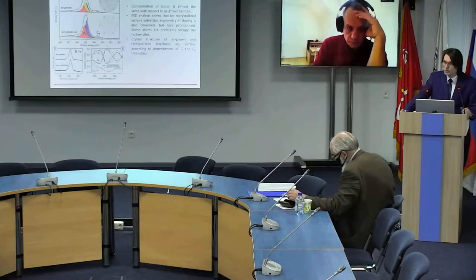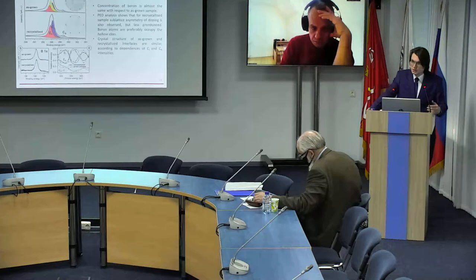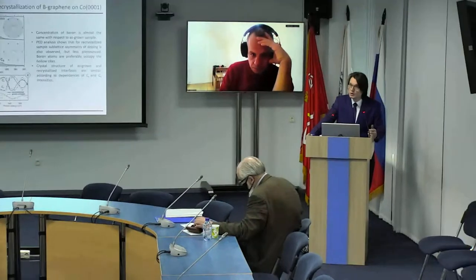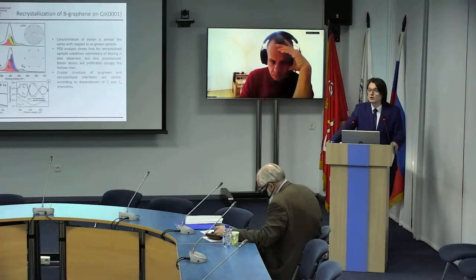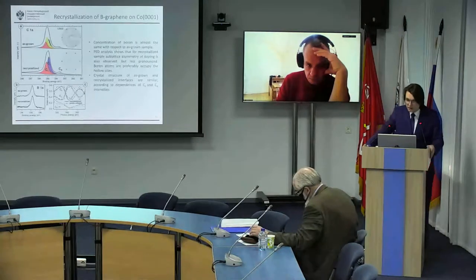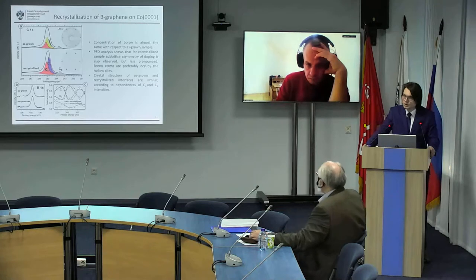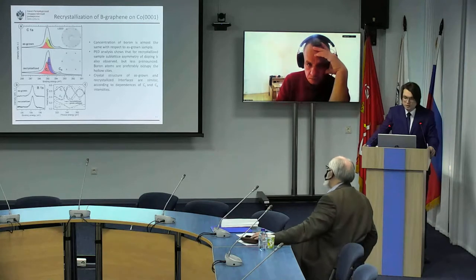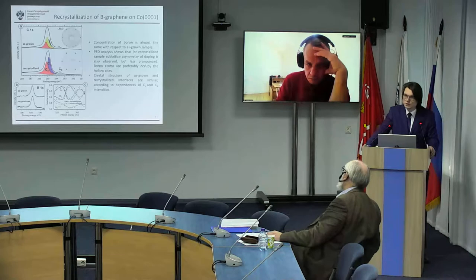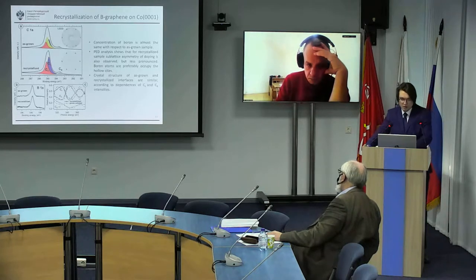And we also carried out recrystallization of B-graphene. It should be mentioned that in the recrystallized sample, the concentration of boron in the lattice of graphene remained unchanged. And the asymmetry of doping of different sublattices with boron atoms was less pronounced than in the case of the synthesized sample.